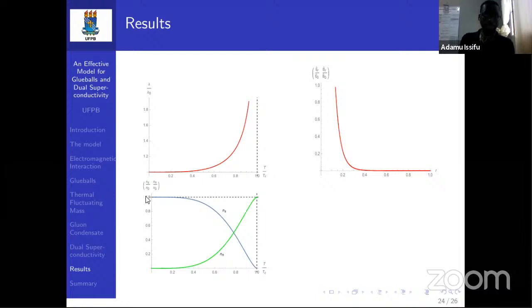And then this is the behavior of the normal monopole number density, and then the superconducting monopole number density and the normal monopole density. We realize that at zero temperature, all the monopoles behave like superconducting monopoles, and then they start decreasing, while the population of the normal monopole starts increasing, and then they get to mix together at a point. This is the point, if you are studying a type 2 superconductor, where the vortices start penetrating the superconductor.